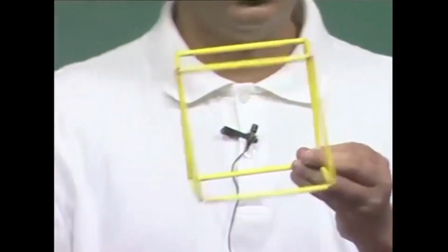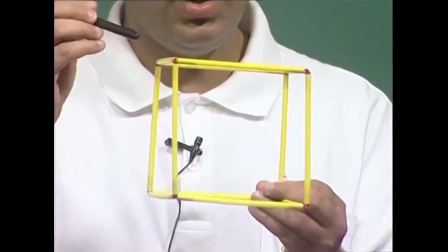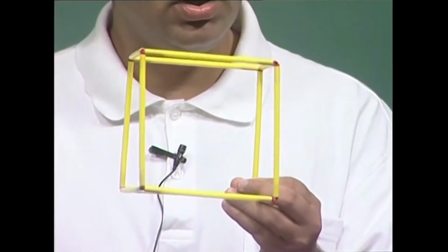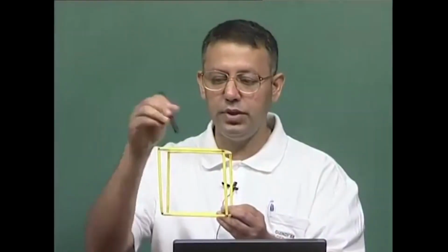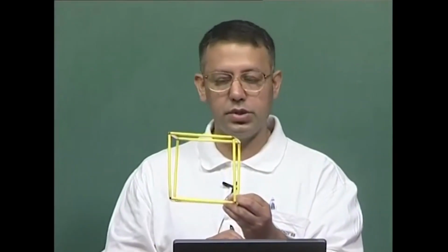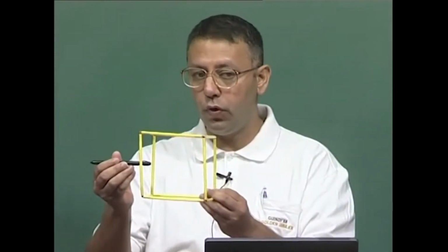Cubic crystals need to have again this 3-fold rotational axis, but cubic lattices always have these 4-fold axes, while cubic crystals need not have any 4-fold rotation axis. Therefore when I am talking about cubic lattices, I need to worry about this 4-fold also.